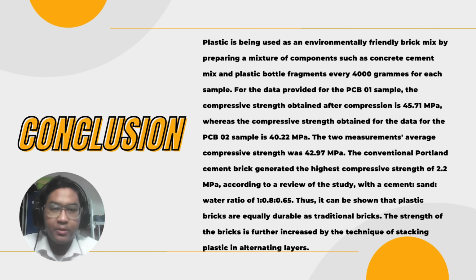Every total of each sample is 4000 grams, which means 4 kilograms. For the data provided from the PCB 01 sample, the compressive strength obtained after compression is 45.71 megapascal, whereas the compressive strength obtained from the data for the PCB 02, the sample 2, is 40.22 megapascal. The two measurements' average compressive strength was 42.97 megapascal.